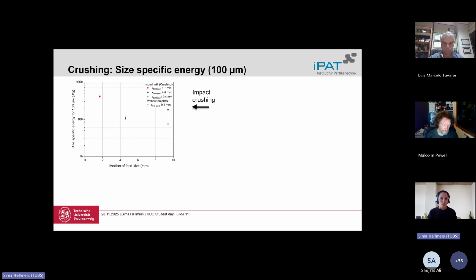And 3 different feed sizes were studied, from 1 millimeter to 1 centimeter. And then the size-specific energy was calculated to see how efficient our process was. And the focus was to achieve 100 micrometer. So why didn't we use the surface? Because the particles were pretty big, so it was difficult to measure the surface. So in this case, we use the size-specific energy, and the higher the size-specific energy is, it means that we are putting too much energy to produce the same fines.